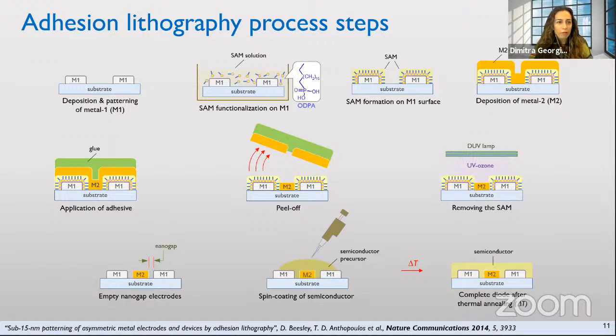We leave it for some time, and what happens is that the functional head, as I explained before, will align and attach to the metal, but not on the substrate. So then we just deposit the second metal everywhere without using any shadow mask or anything more complicated than that, and apply a glue that helps us to peel off the second metal. The interesting part is what happens here during this peeling step.